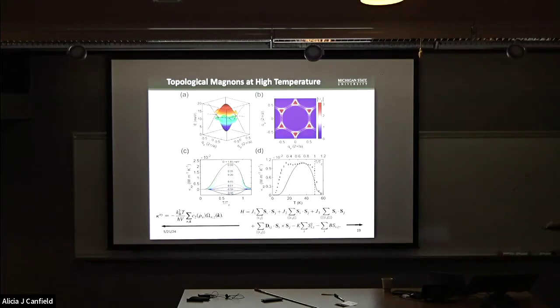And again, as we can see from this equation here, right? And the figure on the bottom right just shows the comparison of our experimental data with the calculated results with 0.2 meV DM interaction. And we can see that the experimental results, which are shown by these red symbols, agree very nicely with the theoretical results.